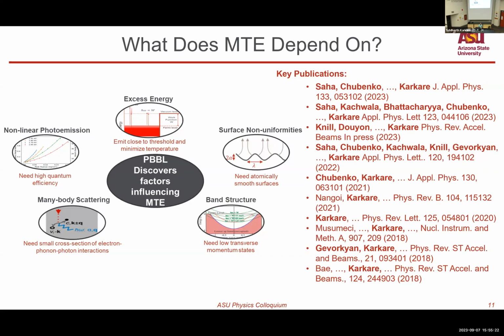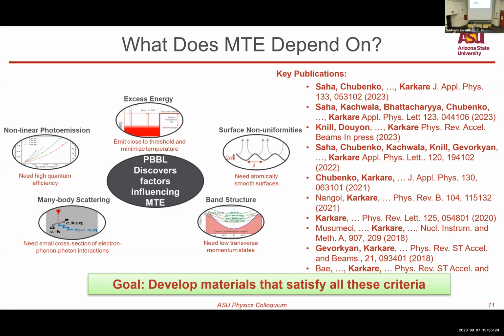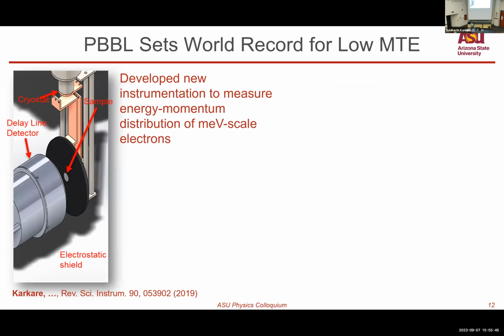So we tried to minimize all of these factors. And our goal is to develop materials that satisfy all of these criteria to get smallest possible mean transverse energy. And we have set a world record for low mean transverse energy. To do that, first we had to develop instrumentation which could measure small mean transverse energies. And that's what we did. We developed this new energy analyzer, which can not only just measure mean transverse energy, but give us the complete three-dimensional energy momentum distribution of emitted electrons, or electrons emitted with very low energies, milli-electron volt scale energies.